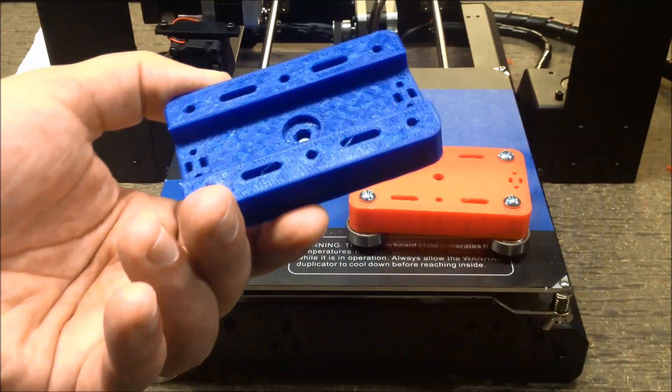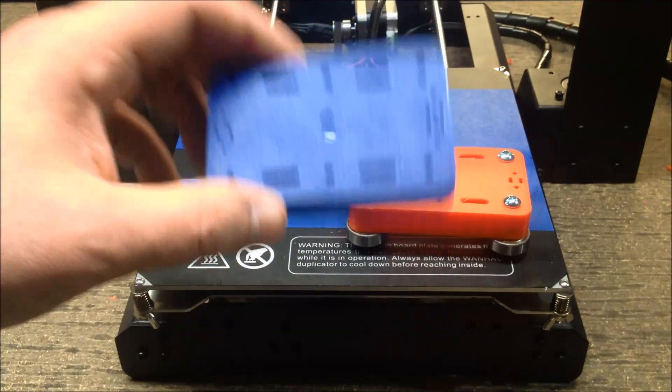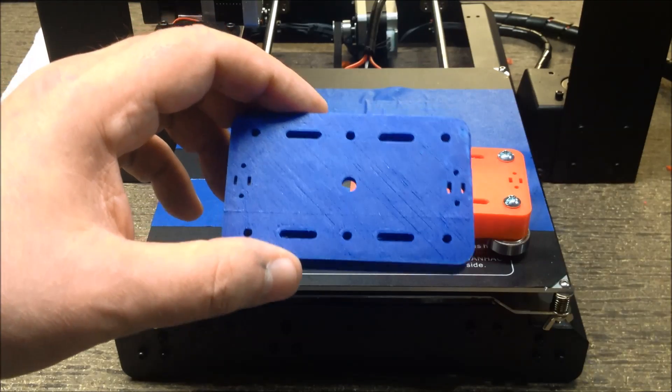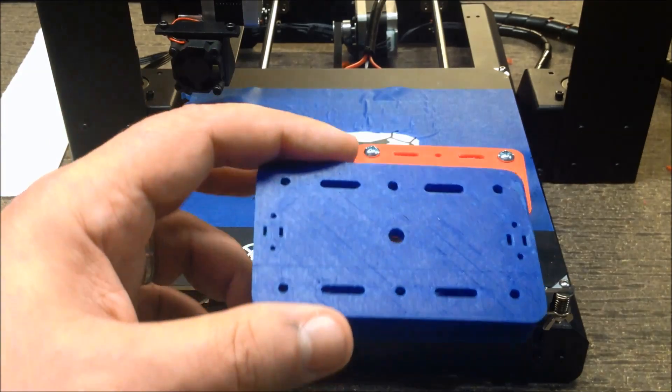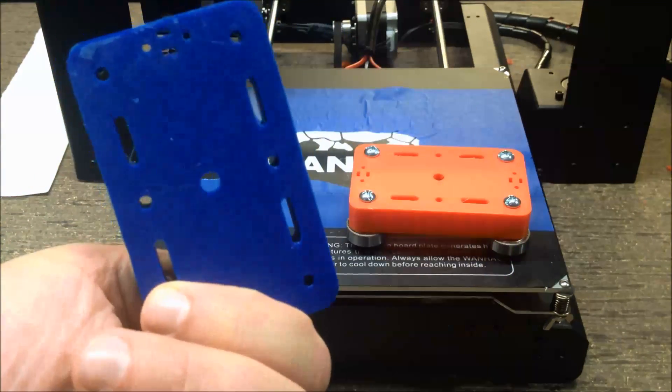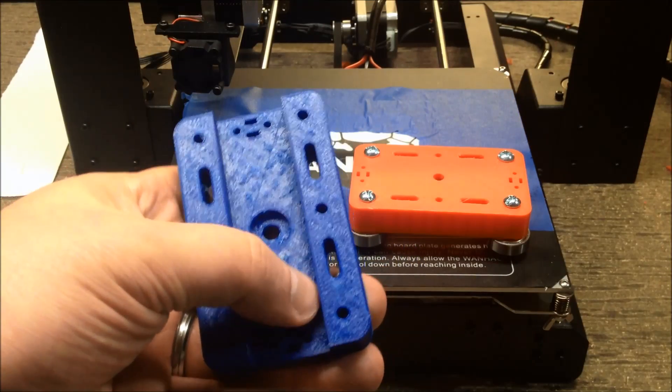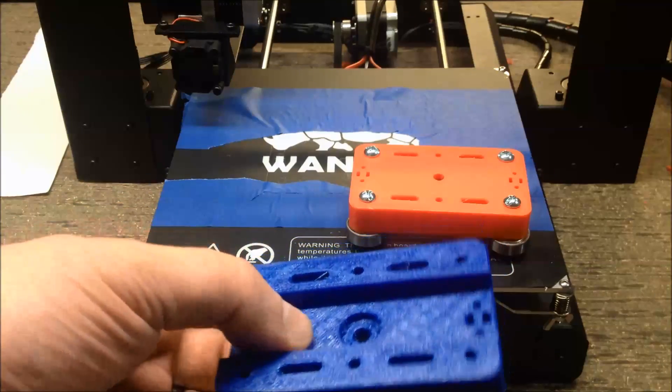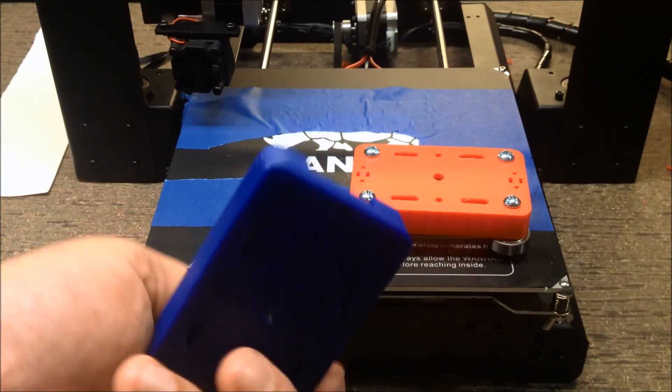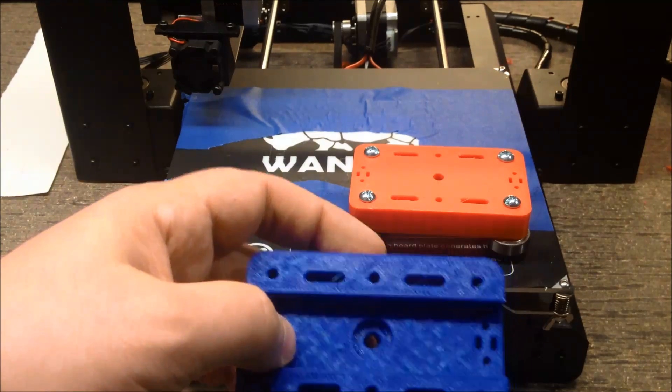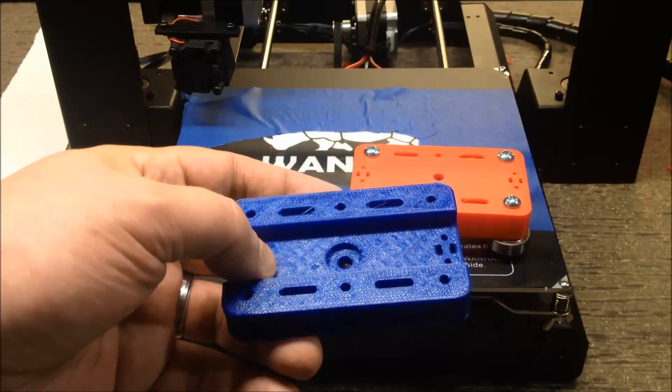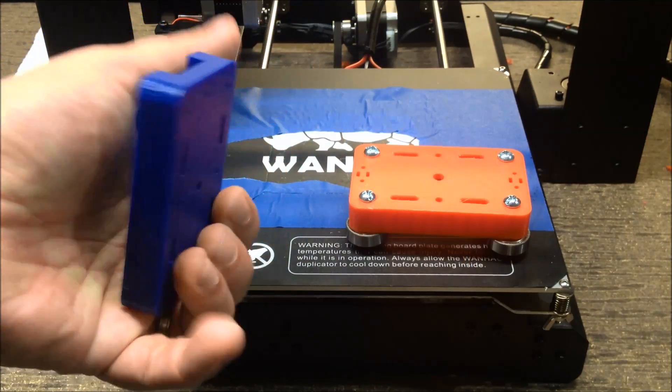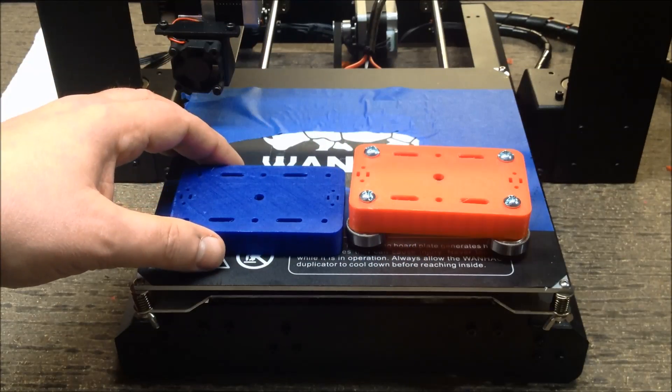I did this at hot-end temperature of 260C, bed temperature of 90 on blue painter's tape. It came out very nice, very happy with the output. I would probably give it a 9 out of 10. The only addition might be an extra layer to kind of fill out some of the dimpling that you can probably see here in the camera over the honeycombs. But outside of that, structurally, it's very, very solid.